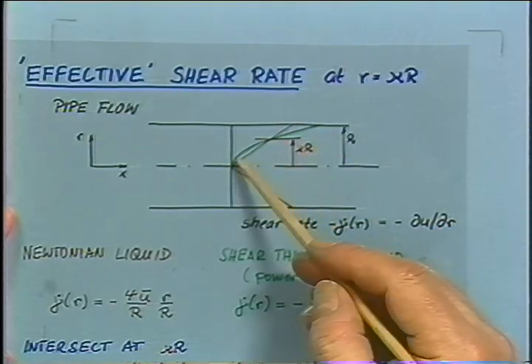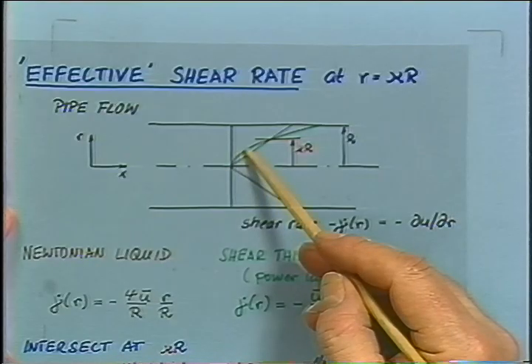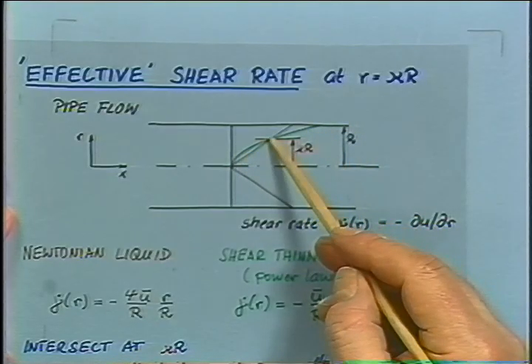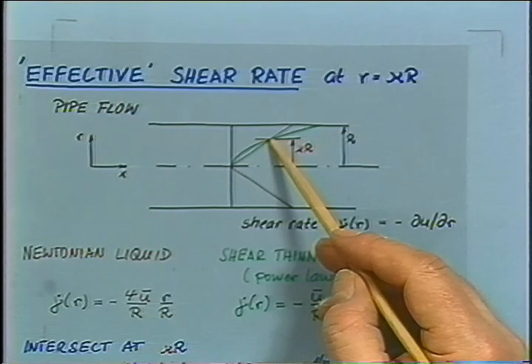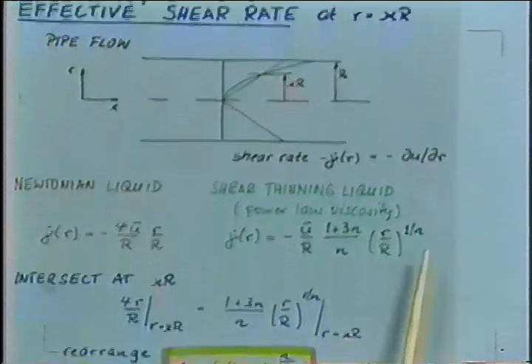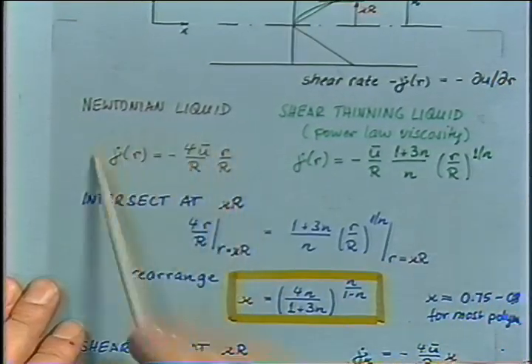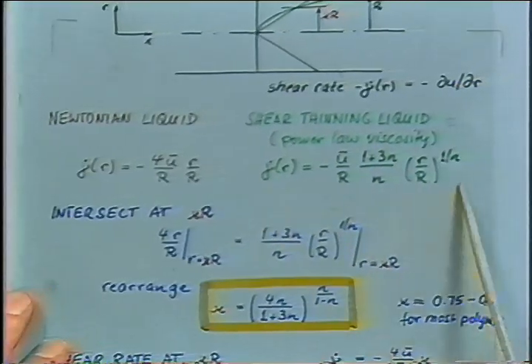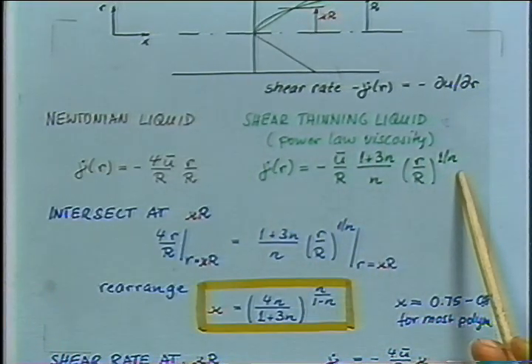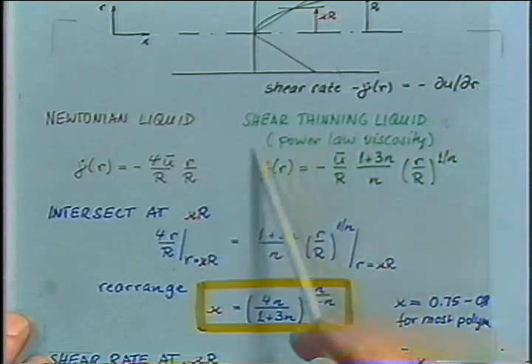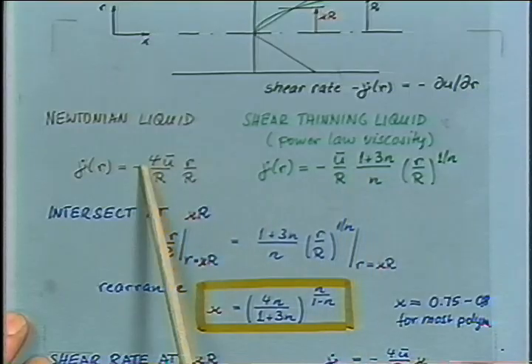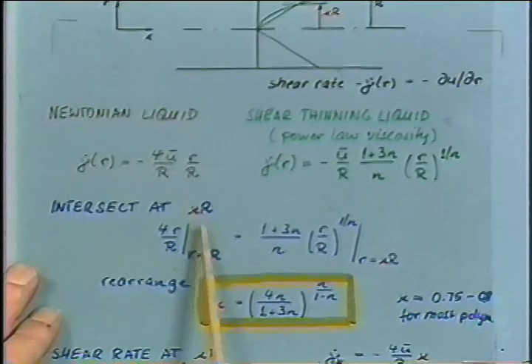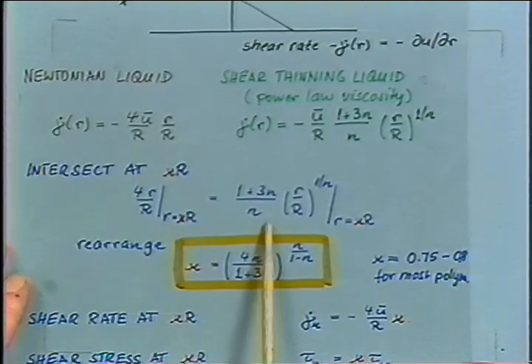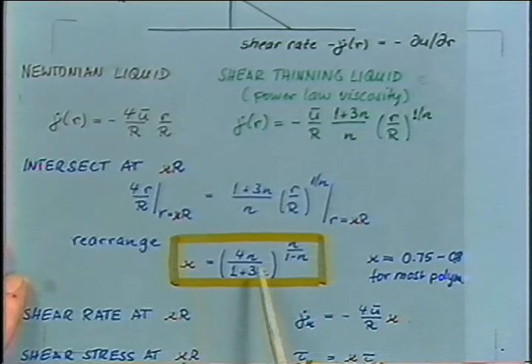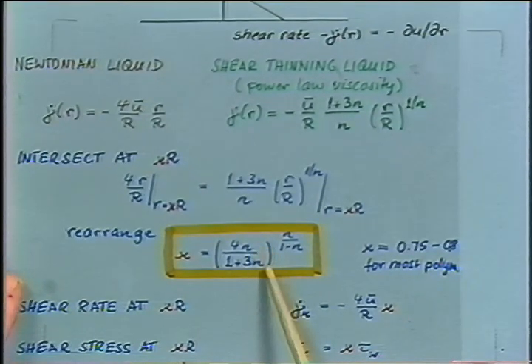But note that in the center part of the capillary, the shear rate is lower for the shear thinning liquid, and near the wall, it's higher, and there's just one crossover point. So there's one radial position for which the shear rate is the same for the Newtonian liquid and for our shear thinning sample. We could calculate that position in terms of the linear analysis for the Newtonian liquid and in terms of a power law analysis, which requires a model. It's not precise, but with this model analysis, we would get the shear rate distribution, and we put those two equal to determine the radial position, kappa times r, for which both of those shear rates are equal. And kappa then is determined like this, and it's a function of the power law exponent n.